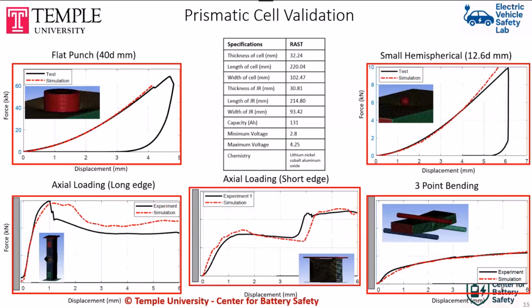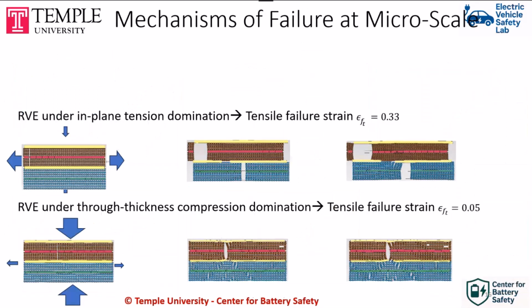So now with this model, we have been able to predict the force displacement and shape of the deformation in a variety of loading conditions: through thickness, bending, in-plane loading in the short direction, and in the long direction. And this is for a prismatic cell. Our results for pouch and cylindrical cells are usually much better than this, but prismatic cells are way more challenging. That was the material model.